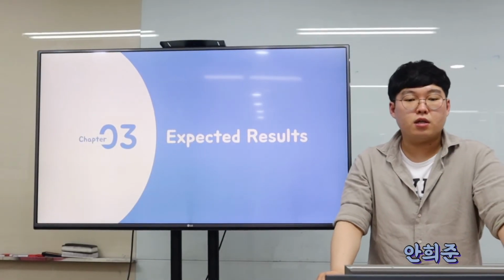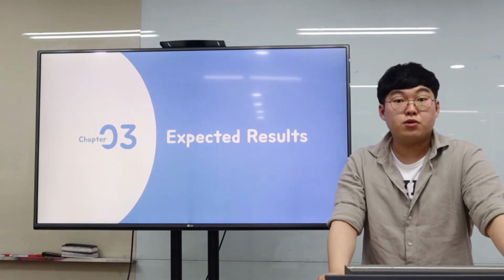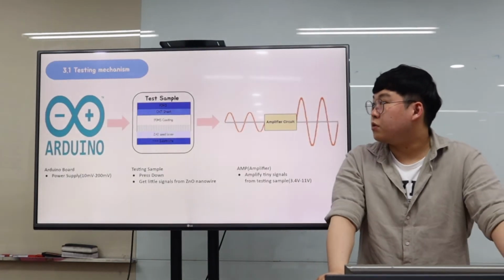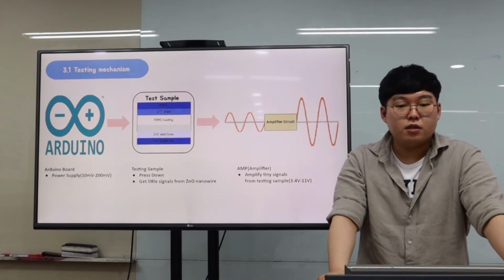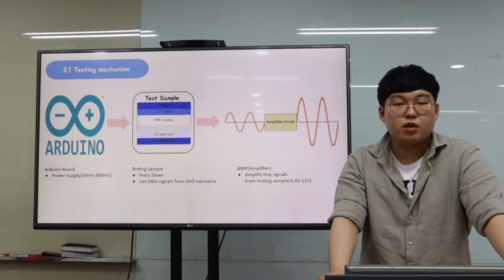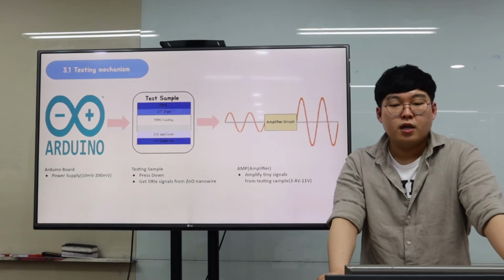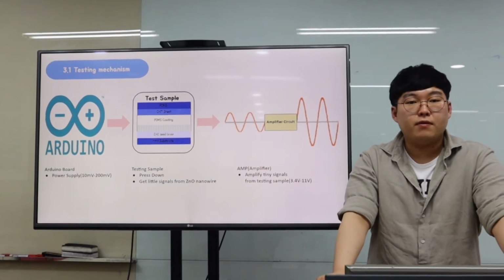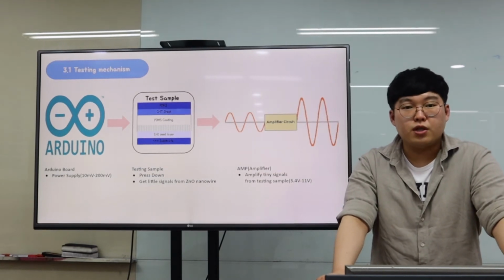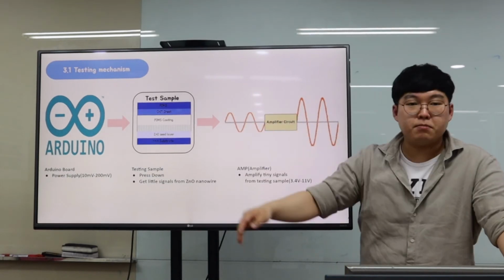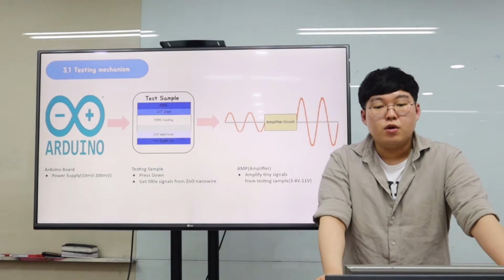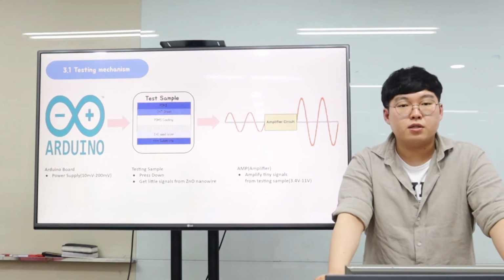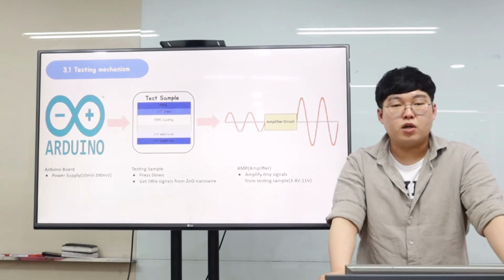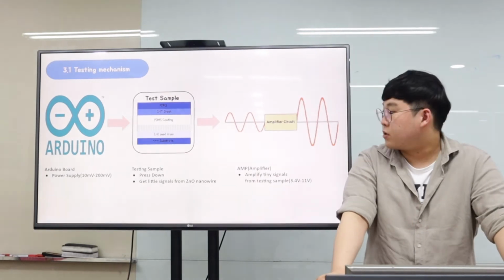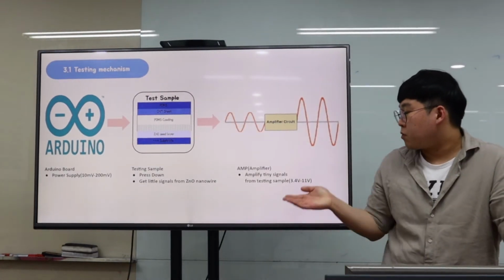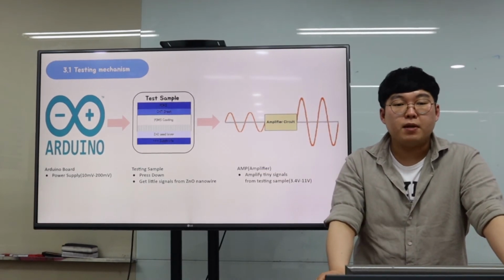Hi, my name is An Hee-jun and I'm going to talk about the expected result part. We measured based on the fabricated sample. So this is our testing mechanism. First, we scratch the sample a little bit and then coat a little amount of silver paste on it. Then we put in a voltage of 10 millivolts to 200 millivolts through the Arduino board. Next, when we press down the samples, we can get small signals. So we use the AMP amplifier for measurements. The reason why we use the AMP is to amplify tiny signals from zinc oxide nanowires. As a result, we can gain 3.4 volts to 11 volts by amplifying the circuit.